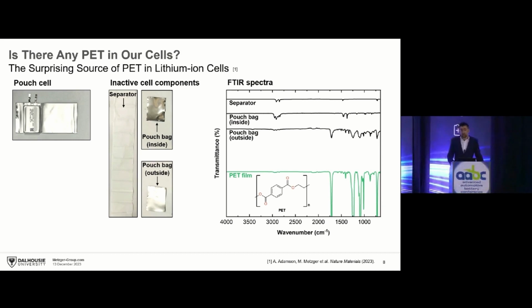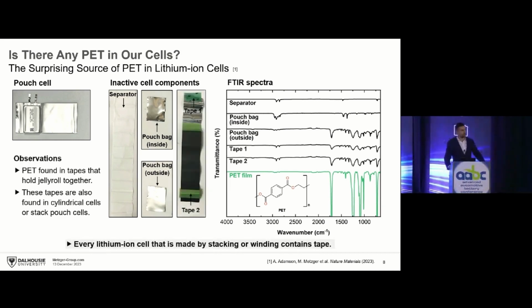But then we looked at the electrodes, and this is the unrolled electrode from this pouch cell, and you can see there are all kinds of tapes on the electrode, right? So there is a closure tape up top, and then there are also tapes where the current collector tabs are. And in fact, if you look at the infrared spectrum, these tapes show all the characteristic absorption bands of PET. So these tapes are made of PET. And you have to realize every lithium-ion cell that's made in the world, if you make it by winding or by stacking the electrodes, would have tape to secure the jelly roll in place in the manufacturing process.